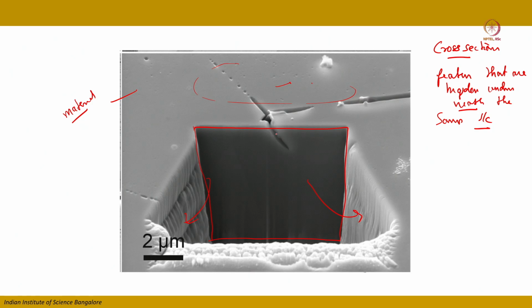So here you can see there is a grain boundary, and by cross section you can see how the crack is propagating along the grain boundary, which is not visible from the top surface, correct. So this is the cross section sample preparation.